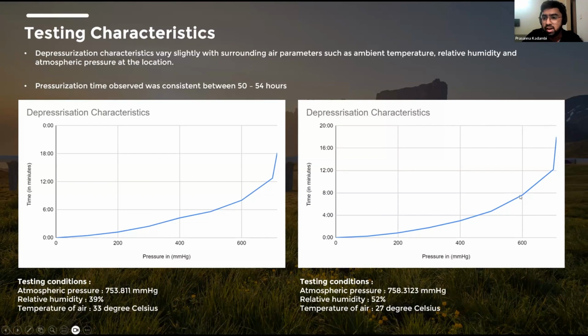Whereas in this case, there is a very steep curve. If you look at a time during the evening, when the relative humidity is more, the temperature of the air has lessened significantly, and the atmospheric pressure doesn't really change much, but there is definitely a change. So this is the kind of observance that we are trying to make, in terms of data capabilities, so that we can analyze and try to have a material structure which will not necessarily be independent, but would not be much influenced by these testing conditions.